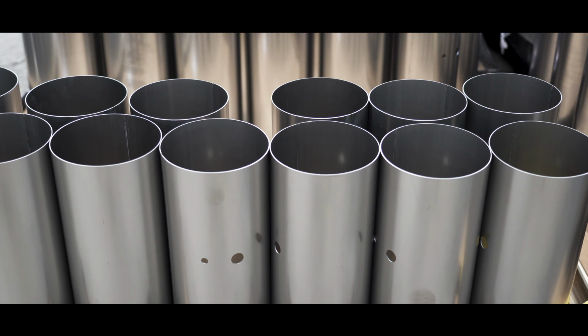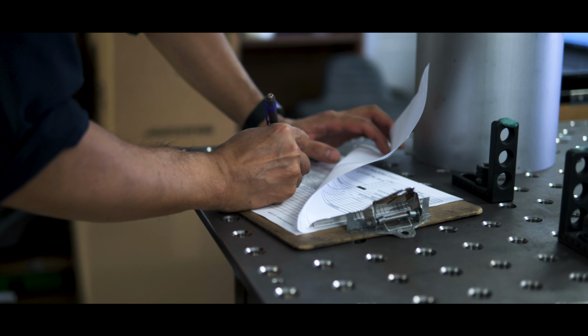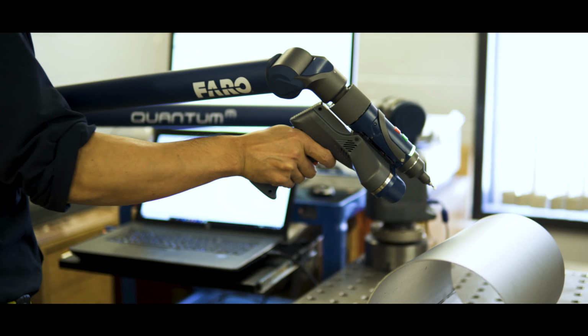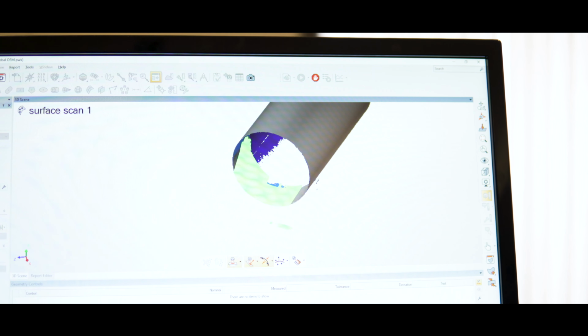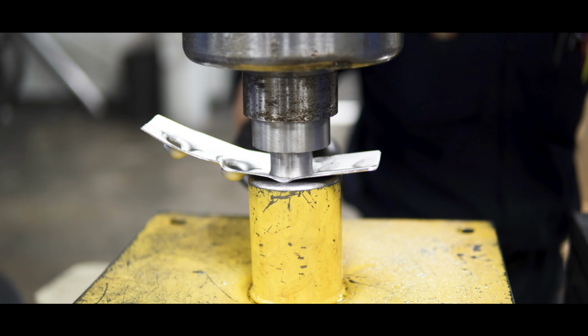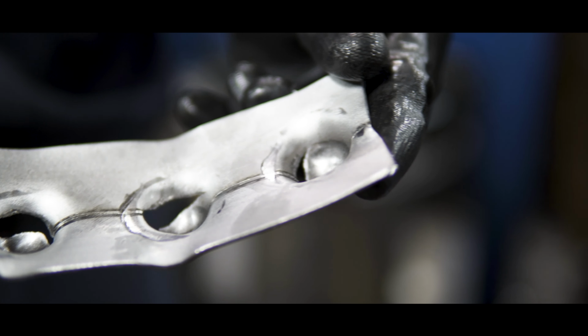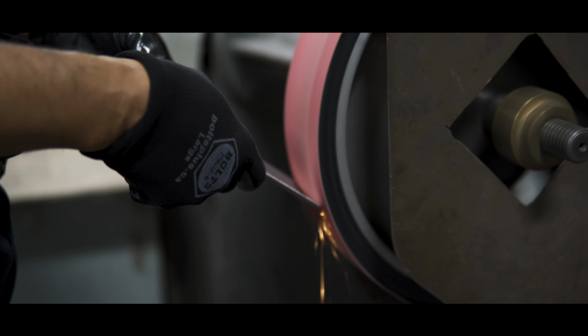When you bought your first Weil machine, you were advancing the company into laser welding. How has that investment paid off in terms of weld quality? Both the laser and the TIG, in fact, have allowed us to expand into formable areas we were never able to do before. The size of our previous heat-affected zones were huge, the welds were lumpy, and as a result, when you had to make a deep V-groove or the equivalent in metal spinning, you would get constant cracking.